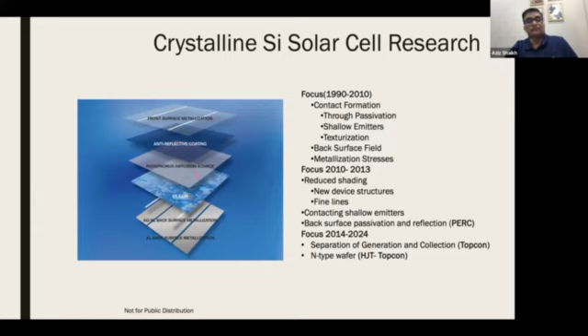Then you form a junction. If this is a p-type silicon, then you would do phosphorus diffusion to form NP junction. If it is an N-type silicon, you would do boron diffusion to form PN junction. Then you put some sort of anti-reflective coating, which is silicon nitride, which reduces the reflection. If you take pure silicon wafer, the reflection is close to 30+%. So you have to put anti-reflective coating. So 30% of the energy could have been lost, which is really not lost because you have anti-reflective coating.